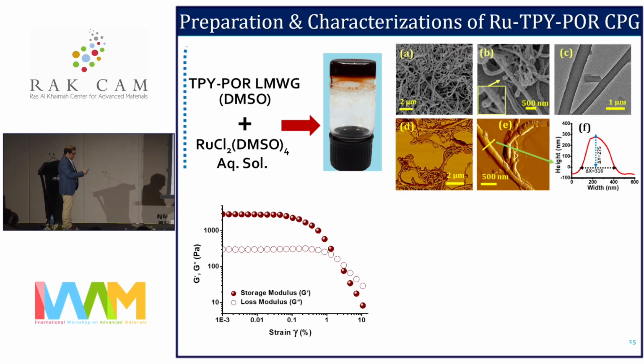It was like a seed kind of structure in the organogel without ruthenium, but it changed to this kind of nanoscroll morphology, which changed the rheology properties, the G prime significantly enhanced compared to the organogel.